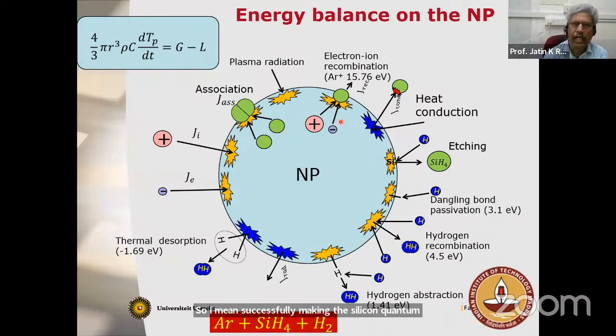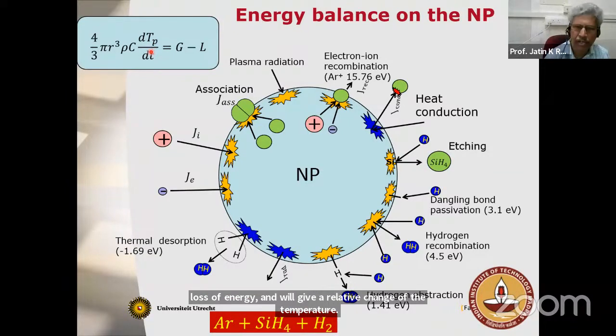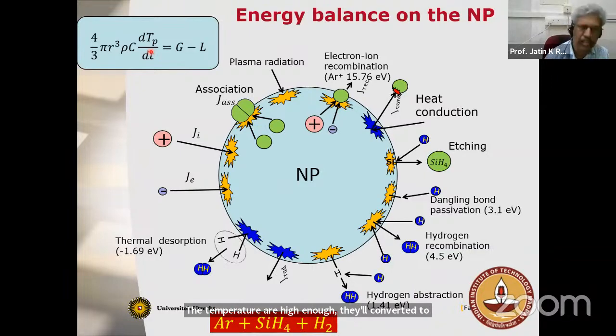And why the quantum dot is formed in the gas phase has been a debate for a long time. One can understand how the nanocrystals form on the surface, but how are they formed in the gas phase? So this is just dust particles, which you can get from various sources. Energy can be transferred to the dust, which is primarily a beginning amorphous cluster, and they will gain energy by different processes. These blue ones are the ones by which they lose energy. For example, the hydrogen recombination reaction on the surface will give them energy. Etching also, abstraction also, they will gain energy. If this energy is more than what is necessary for crystallization, they'll convert to crystals. Basically, the change of the temperature is given by this equation, and this is the generation of energy, and this is the loss of energy, and it will give you the rate of change of the temperature. If the temperature is high enough, they'll convert to crystal. So that's why the crystalline quantum dots are formed in the gas phase itself.